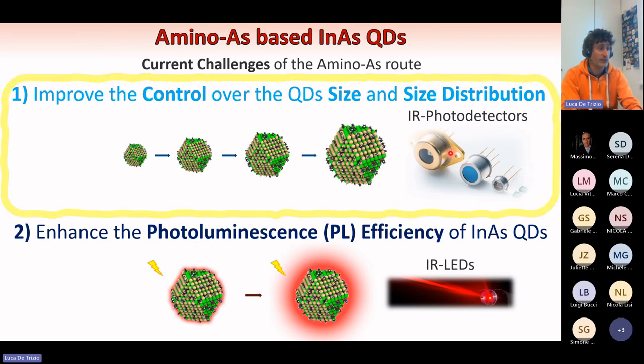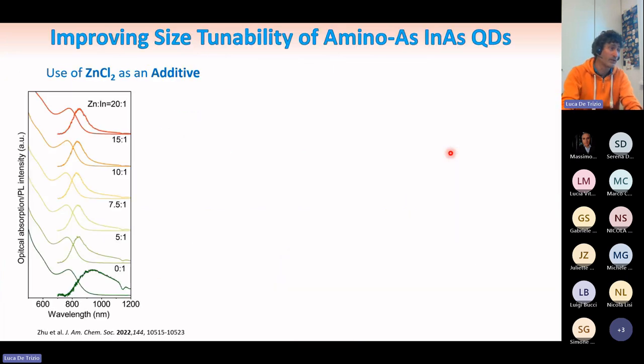Regarding the first point, in the IEMAP framework, in a first work published a couple of years ago, we tried to improve the size distribution by employing zinc as an additive. Here you can see the absorption curves and the PL curves of the samples we made.